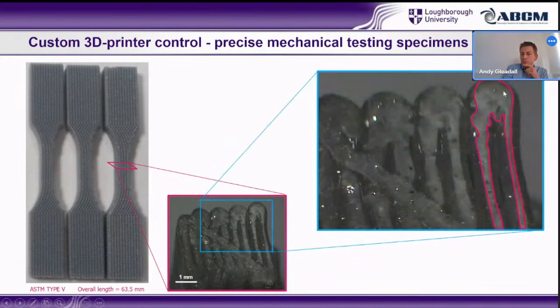So this pink outline is showing what the actual bonded area was of this line here. There's this diagonal line as well. That's when the nozzle actually moved from the end of one layer to the beginning of the next. It's not supposed to print. It's not part of the design. It's just something that had to happen between layers. But clearly it's significantly affected the actual interlayer bond.